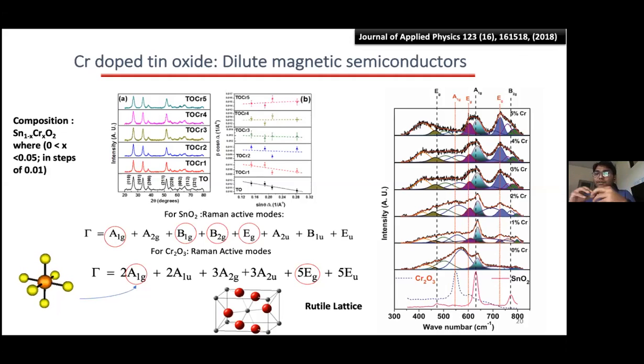If you are looking at the lattice vibration of these octahedra of 6 oxygens with tin, the SnO6 octahedra, and similarly you look at the octahedra of CrO6, you will see that if you are replacing tin with this different charge ion, instead of 4 plus, you are creating one vacancy in one of these 6 oxygen sites, and effectively this symmetric stretching which is happening will not be there. So that particular mode of Raman excitation is killed systematically. And as you go on doping more and more of this different nuclear charge, you will see that this mode gets killed systematically, and other modes start to show up, which are basically ascribed to the foreign atom, the new one.